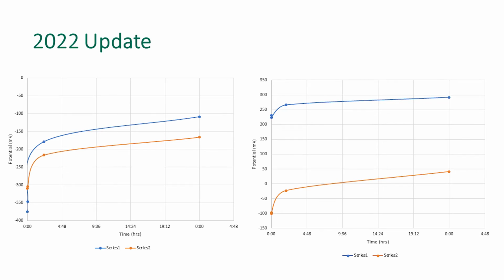And so we left site around November 2020, but we actually went back this March to collect a little bit of data and just to see that the anodes are still performing correctly and everything's going well. And so we did some measurements and polarization testing on all of the zones. If you're not a corrosion professional, really what we want to see is that the value that we measured at time 0 versus this time shows about 100 millivolts of shift. And we're seeing very good shift still in all of the steel. So that tells us that everything is still passive and working really well. So those anodes are actively changing the environment around the steel in those high risk areas and preventing corrosion activity.